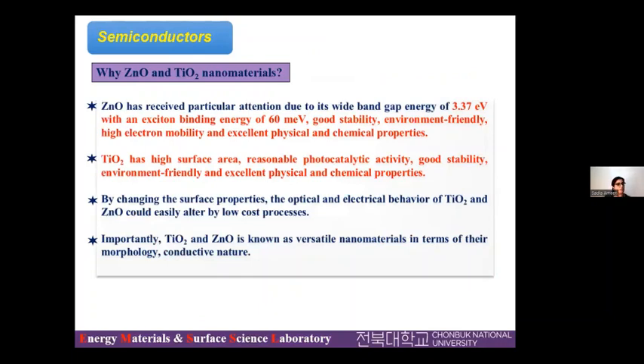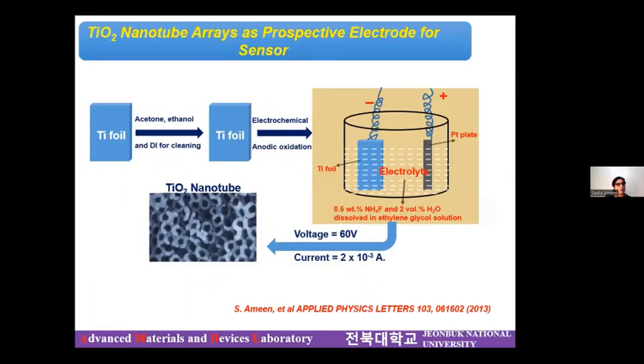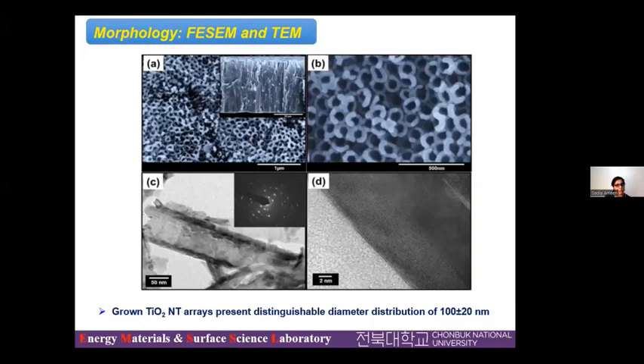The metal oxides that I have specifically taken for this are ZnO and TiO2, because they are highly stable, environmentally friendly, and show excellent physical and chemical properties. And this is how we have synthesized the TiO2 nanotubes over the surface of the Ti foil through the electrochemical method. From the FESEM images, it is quite clear that these nanotubes are aligned and hollow, with a diameter of roughly 100 to 120 nanometers.